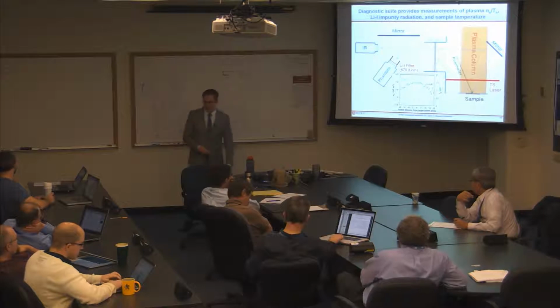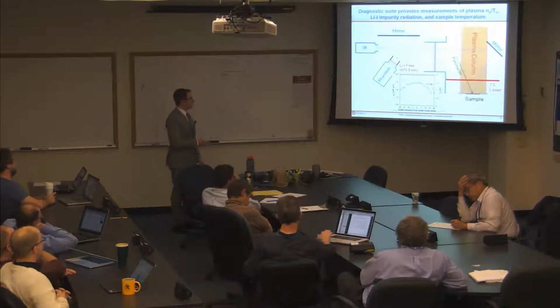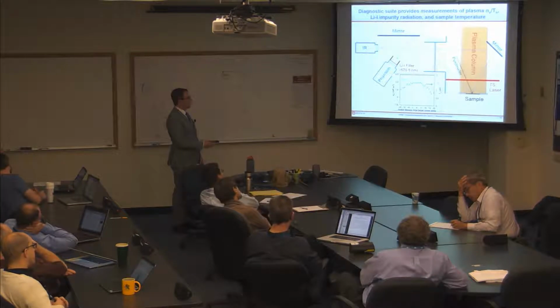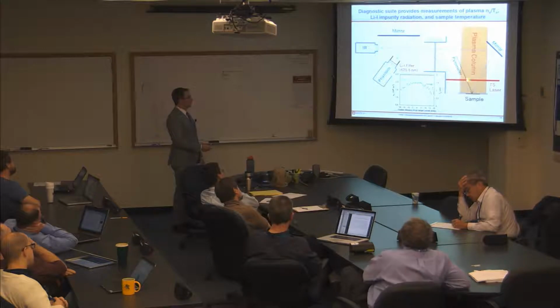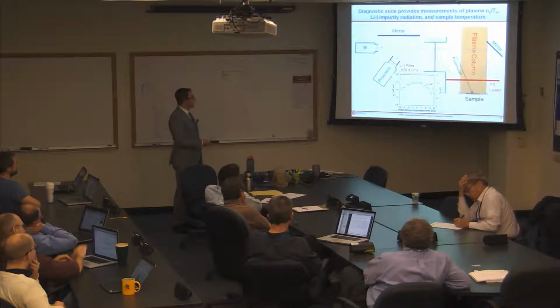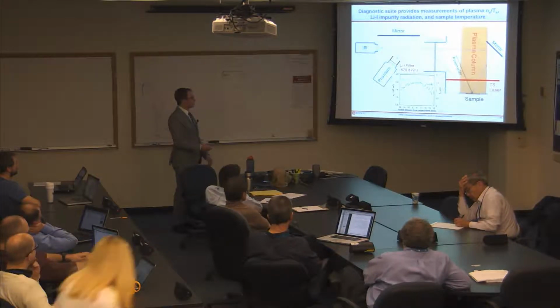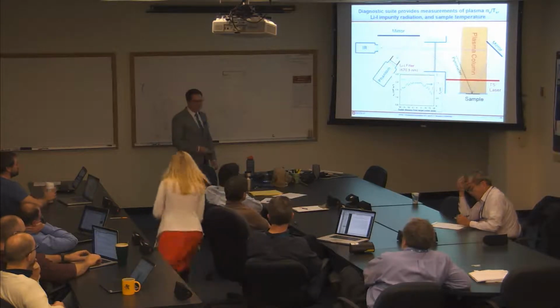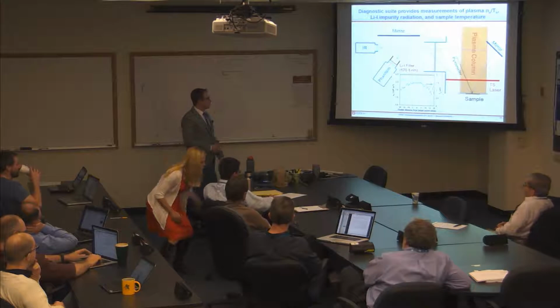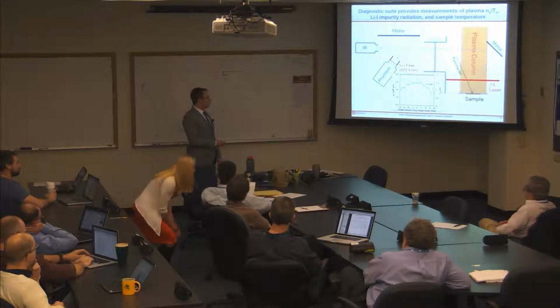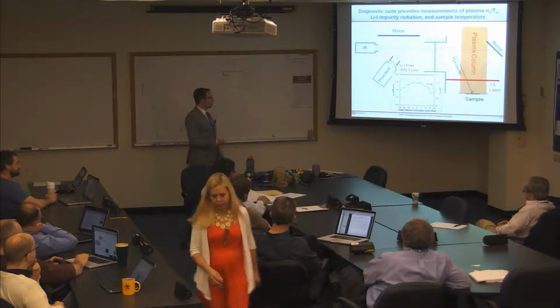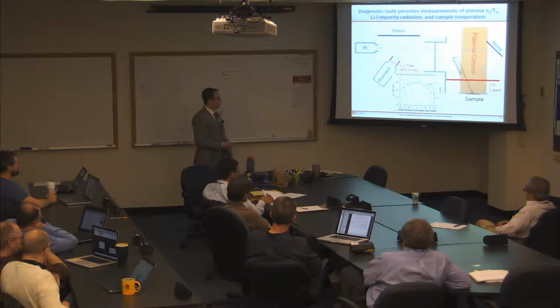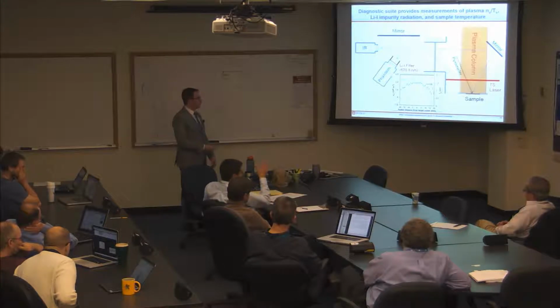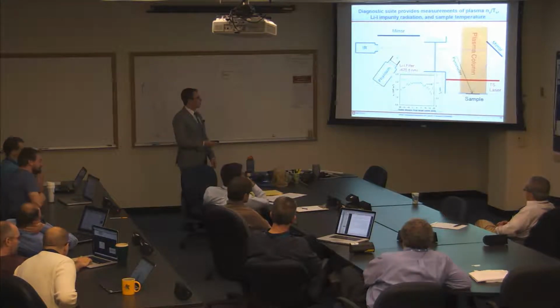Okay, so let me tell you about the diagnostic setup. So this is the plasma column here, and then this is the vacuum break right here. And so all of our diagnostics, for the most part, look through this one window, which is made out of barium fluoride. And so the main surface diagnostics are an infrared camera, which gives you a 2D profile of the sample temperature, and a high-speed visual camera, which has a lithium-1 filter on it, which essentially isolates this one very strong line radiation, the 3-to-2 transition in neutral lithium. So you can essentially measure the line integrated emission rate from lithium atoms alone.